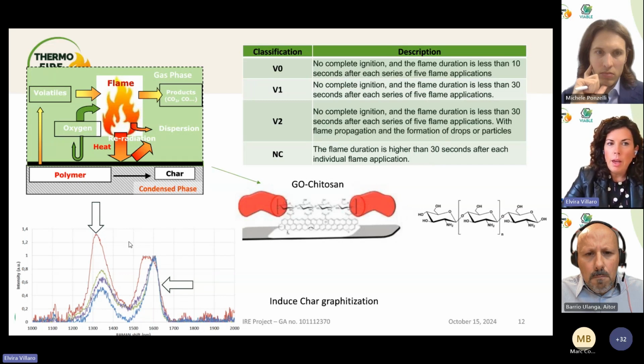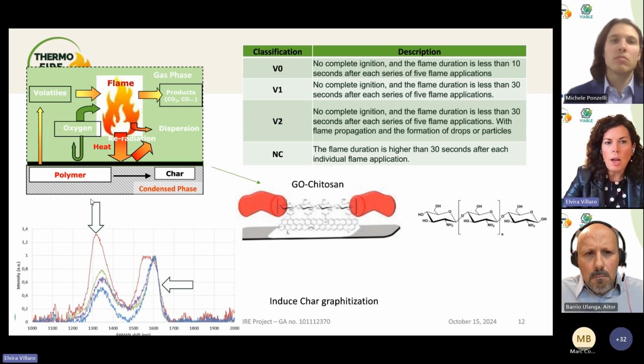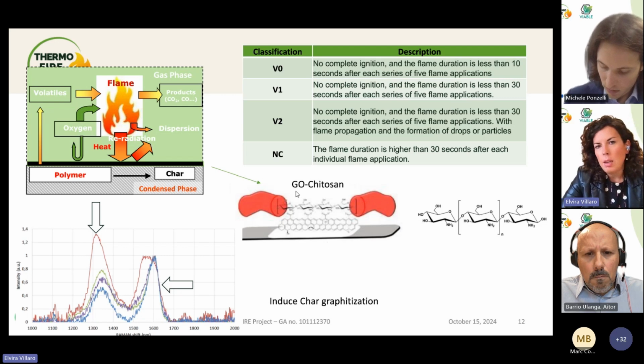When we have exposure to the flame, and we characterize the char, we observe an important decrease in the band, because all this oxygen content has been released during the flame exposure, and we have reduced the material. This is the effect that we can observe, for example, in materials such as graphene oxide or graphene oxide modified with chitosan.